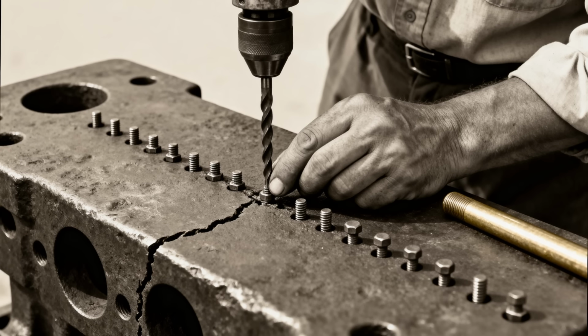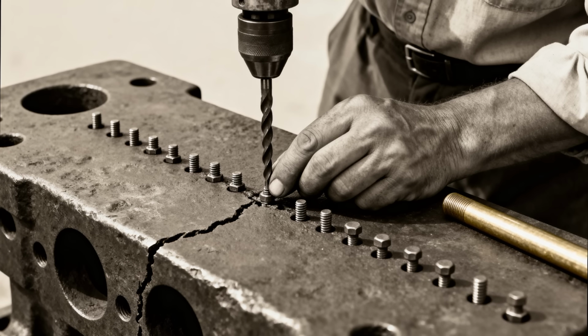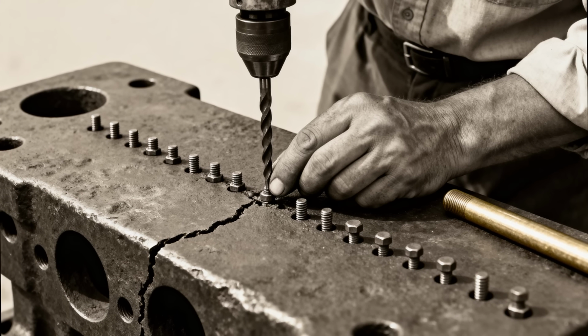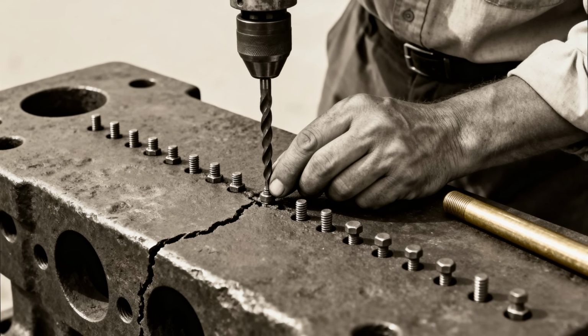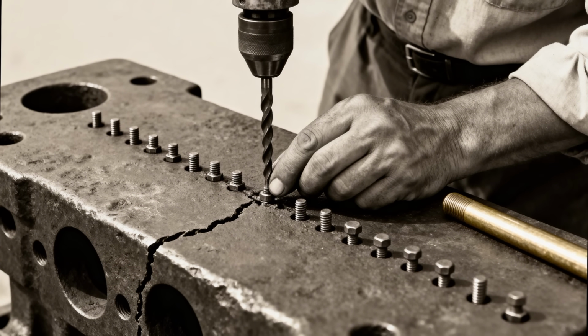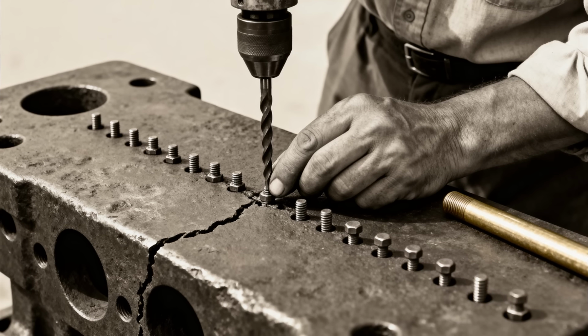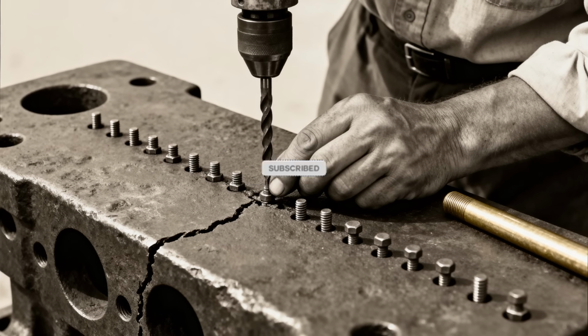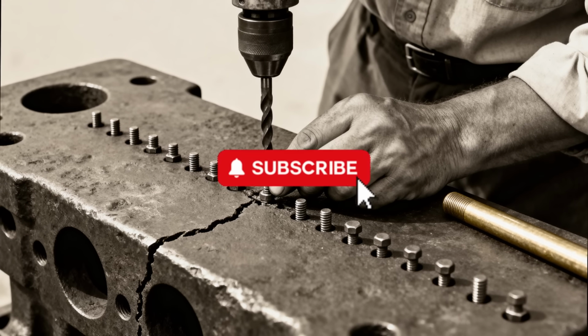The absolute masters of this repair, though, used a method called mechanical locking, combined with brazing. They would drill a series of small holes along both sides of the crack, then thread those holes and screw in soft iron plugs, creating a mechanical connection across the crack. Then they would braze over the entire repair, filling the crack and covering the plugs. This created both a mechanical bond and a sealed joint that could withstand pressure and temperature cycling for decades.